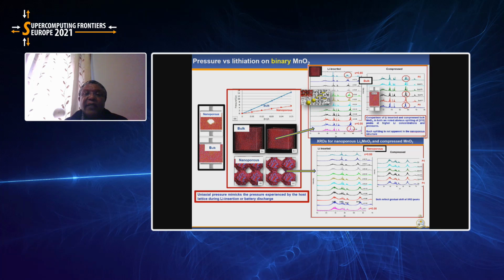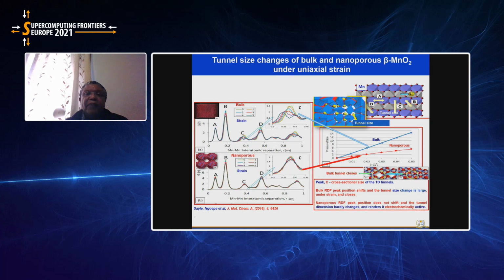When you look at the X-ray patterns, we realize that the patterns split as you apply the pressure or when you put lithium inside that structure. In the case of the nanoporous structure, we realize that these peaks don't split, they just shift towards the left, which means that there isn't much structural change in the porous structure.